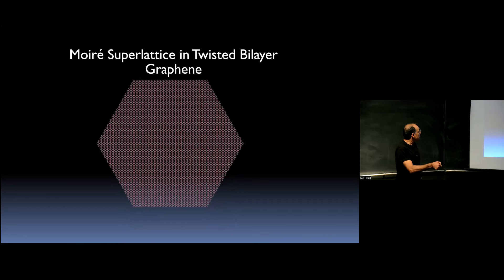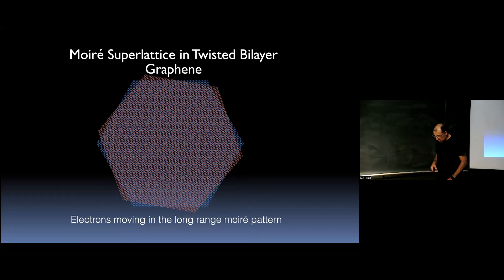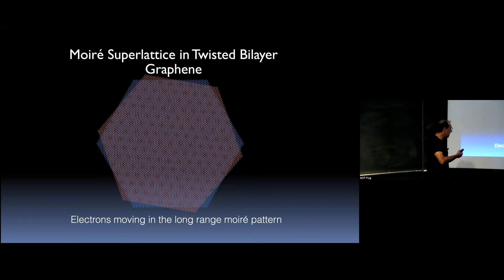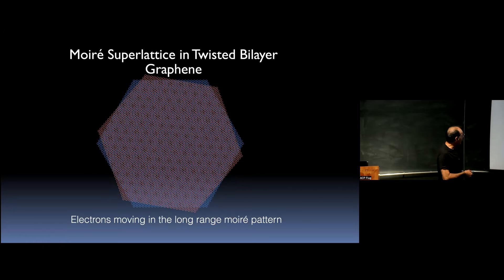This is how this field got started: two sheets of graphene placed on top of one another and twisted a little bit. What you can see is the interference between the two graphene lattices — this is what we call a moiré superlattice, coming from this two-periodic pattern. What we are doing is subjecting electrons to this longer periodicity. It seems like a simple thing, but it has major consequences for what electrons are doing on such a lattice.